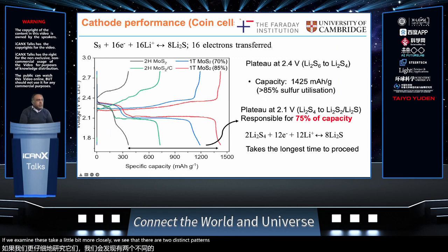If we examine these curves a little bit more closely, we see that there are two distinct plateaus, right? There's one here that happens at around 2.4 volts, and another one, which is the long one here, that happens at around 2.1 volt. This plateau at 2.1 volt is the polysulfide reduction, Li2S4 to Li2S2 or Li2S. And this is responsible for 75% of the capacity of the lithium sulfur battery. It also takes the longest time to proceed. So optimization of this reaction is really the key to having good lithium sulfur batteries.